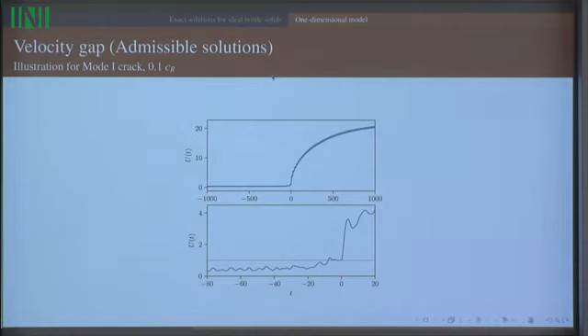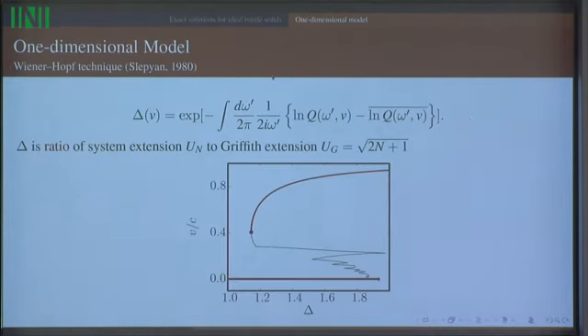And if you solve with the Wiener-Hopf technique at a velocity that's in this region that I said is forbidden, t equals 0 is the point where, according to the math, the bond should first break. But if you look at the solution, I have this just for illustration, then you see that the bond actually went above the breaking point supposedly at a negative time, but the bond didn't break, and then it came down, and then it wiggled around the breaking point for a while, and then it finally decided to break. Now, there are macroscopic objects that could behave like that. You can stretch them too much and then bring them back down, and then they can eventually decide to go. But atomic forces are too perfect to allow that. They break the first time or they never break. That's it.